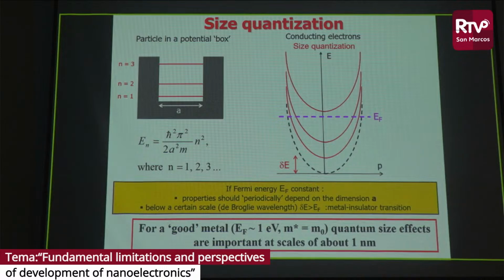What are the numbers behind this story? If we put conventional data for a normal metal, let's say Fermi energy about 1 electron volt and mass equal to the mass of a free electron, it appears that the effect should be observable in conventional metals with these parameters at a scale of 1 nanometer, which is not very easy to do. But if we think a little bit more and look at this formula, one can understand that another option to obtain this regime of strong quantization is to reduce the mass of the particle. And there are materials which are called semimetals, and good representatives are bismuth or antimony, where the mass of the charge carriers is 3 orders smaller than the free electron mass.